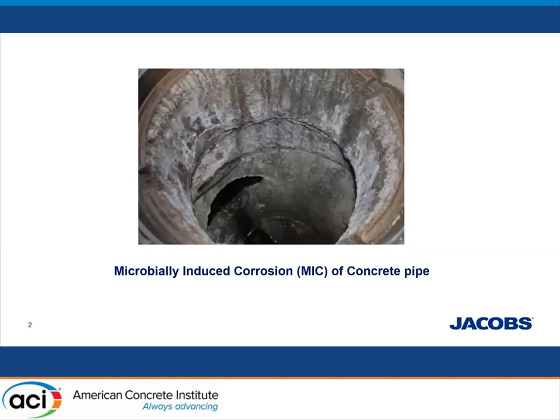As others already mentioned here, concrete pipes are susceptible to chemical and biogenic attacks, key elements to expedite concrete deterioration by corrosion. Microorganisms exist in sewer environments, producing sulfuric acid to accelerate the degradation of concrete pipes in a process termed microbially induced corrosion.